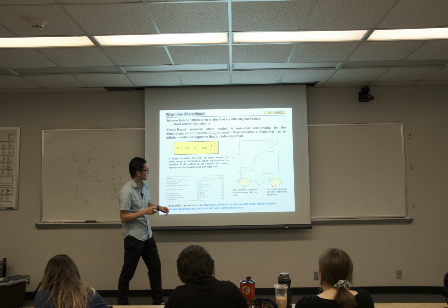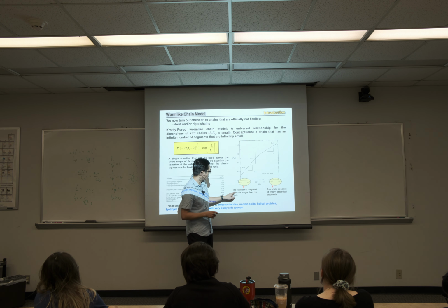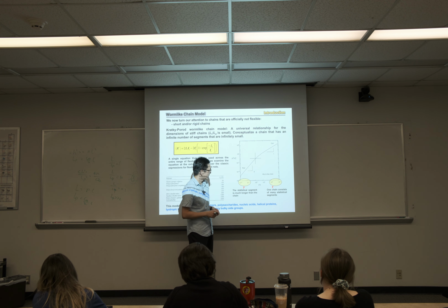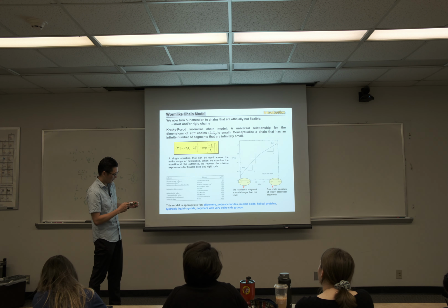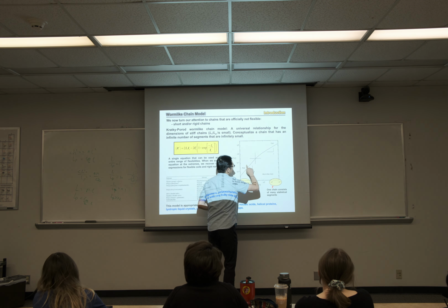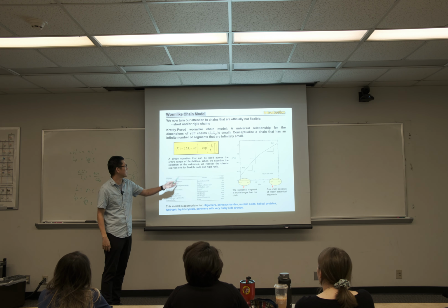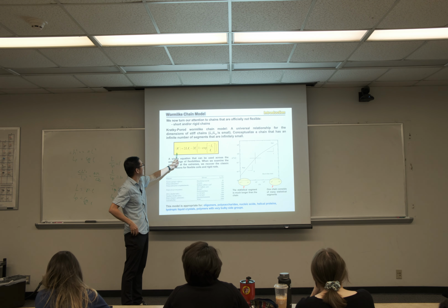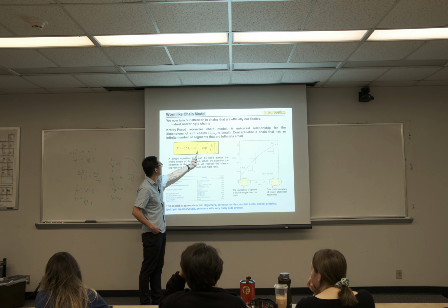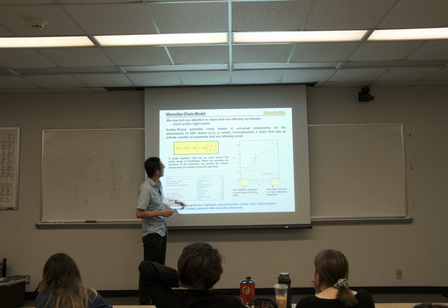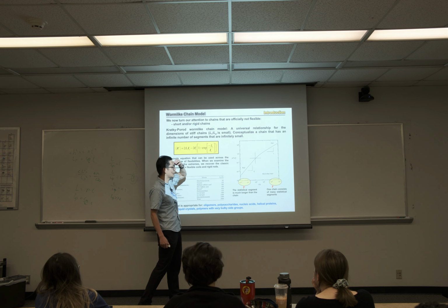So this we typically call a rod-like chain. The statistical segment is much longer than the chain. On the other hand, this side is more flexible. So the worm-like chain basically can describe something in between, in this region where it's not a coil, but it's not a rod yet. It's semi-flexible, where we can use end-to-end distance squared equals 2 times L_C times LP minus 2 times LP squared times 1 minus exponent of minus L_C divided by LP.